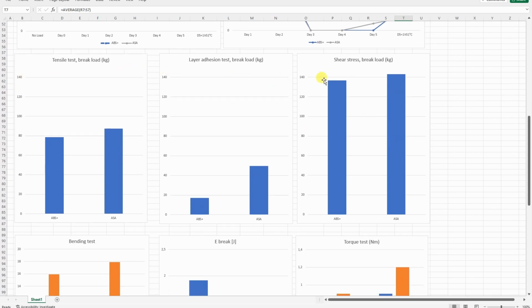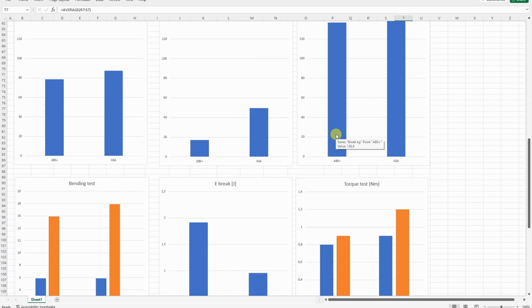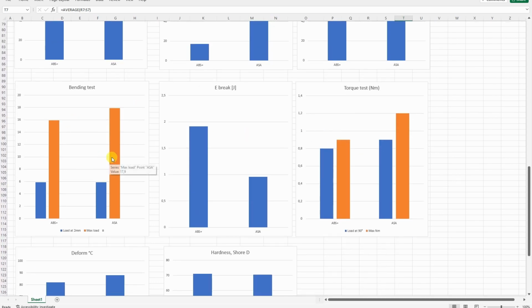And here the scale is equal, so from these three I think this is the most important to mention, the layer adhesion. With ASA it was 2.5 times bigger than ABS plus, and for most applications this is extremely important for me. For the tensile test and shear stress, it's very similar, so I wouldn't say there is any big difference. The bending test very similar, and the torque test also, and here again we have a bigger difference, but now ABS plus is much better in that impact test. And actually this is just guessing because the test specimen didn't break.